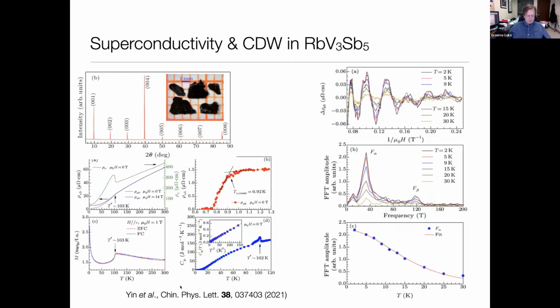Another group, people jumped onto this fairly quickly. A group in China managed to make the rubidium version of this material in single crystal form. You can see some of these crystals here. They're grown by a flux method. You see beautiful scattering patterns there. Again, the charge density wave opens up, at about 103 Kelvin in this material. You see it in the susceptibility as well. You see about a 1 Kelvin superconducting transition, a little bit broad in the resistance of this sample here. But it's certainly a bulk superconductor.